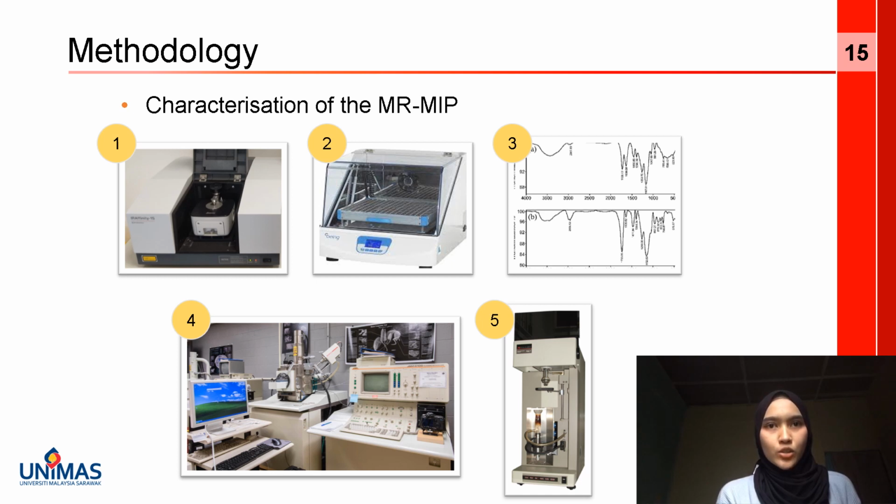A scanning electron microscope, SEM, will be used to obtain electron micrographs to evaluate the morphology and surface structure. All the samples will be analyzed on an aluminum stub coated under a vacuum with a thin gold layer. The thermal analysis will be carried out using the TGA instrument.